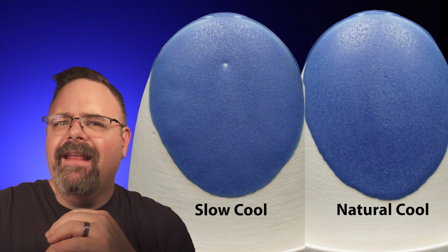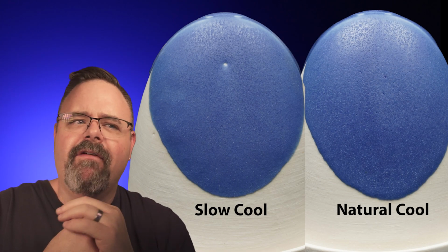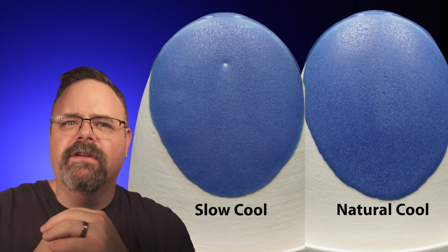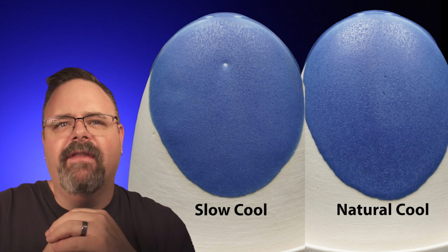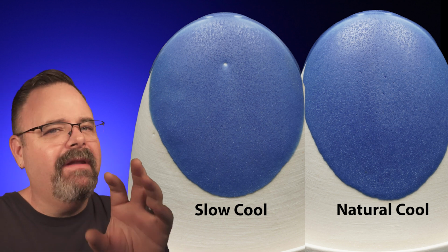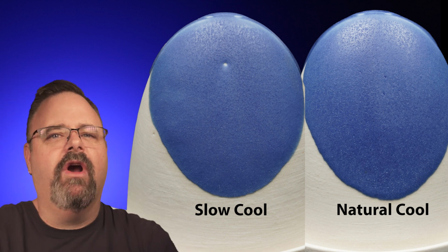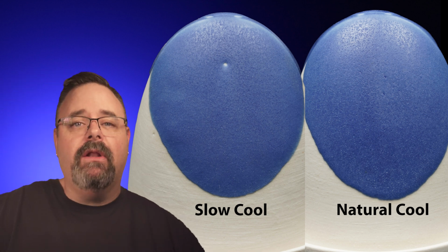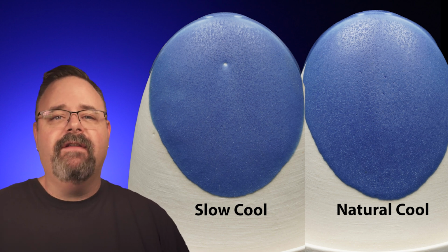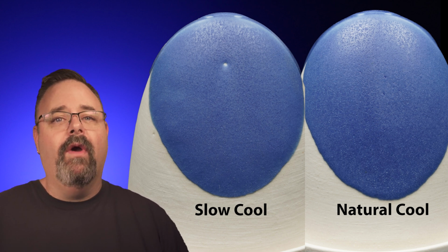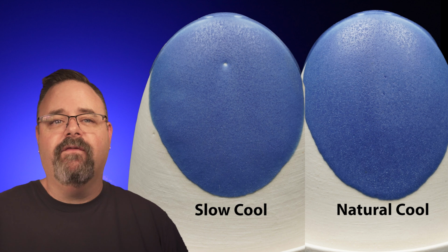The other thing that you might hear about certain types of glazes, specifically matte glazes, is that they really benefit from slow cooling. That is not true with matte glazes. If you have a matte glaze that falls in the matte region of Stull's map, it does not care how that glaze is cooled. It's the instability of the alumina that's forcing the crystals to grow, and they're going to happen no matter what, because that alumina is there. And if it does not have a place to go, it is going to find a place to go, and that is forming those crystals. So matte glazes on Stull don't care about slow cooling.